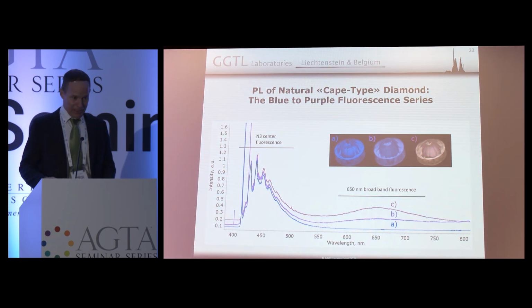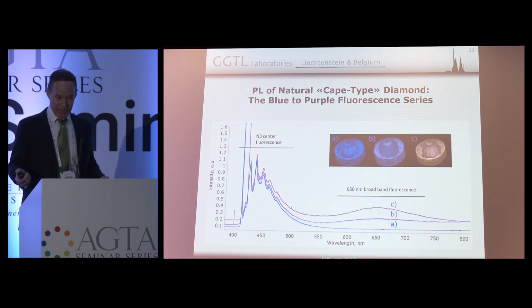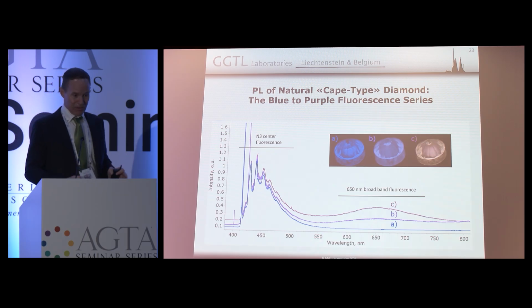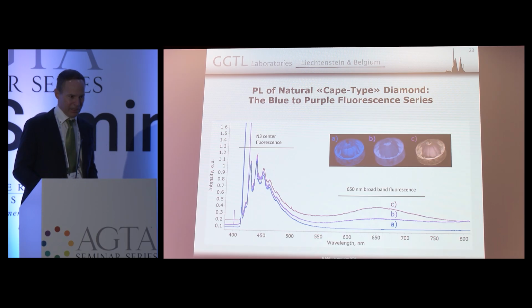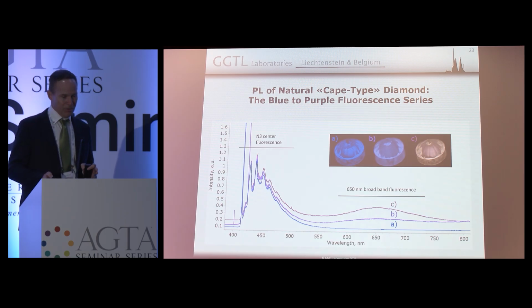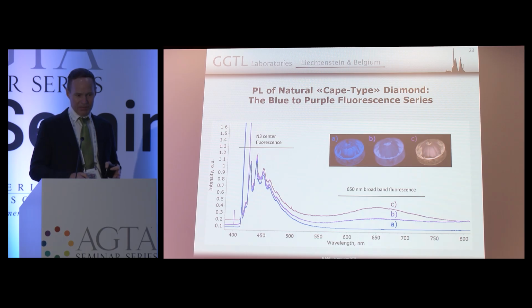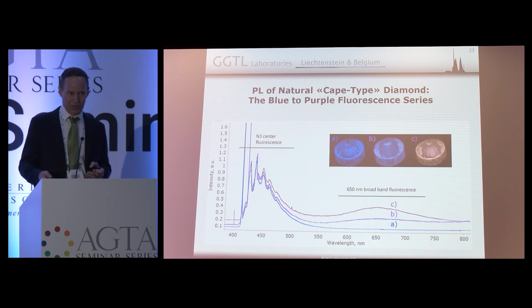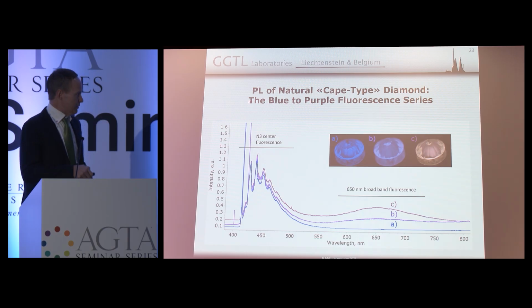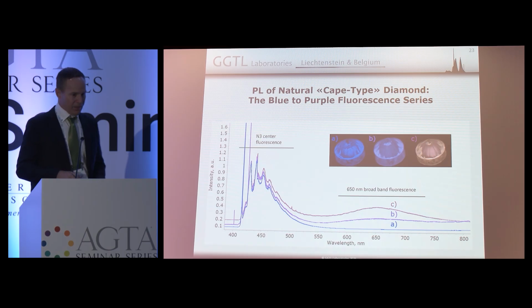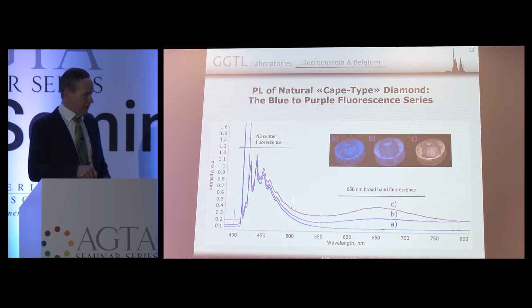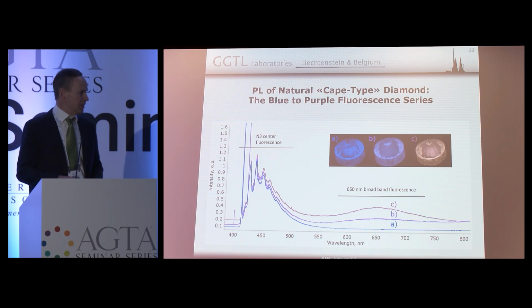So just to give you an idea, the most common defect when we look at these stones, the one thing that most systems that do currently automatic testing look for is this, okay? When we do fluorescence imaging and at the same time quickly look at the spectrum, our system looks for this center here. If you have a distinct N3 center in a colorless diamond, or in a colorless to near colorless diamond, you know it is still of natural origin.